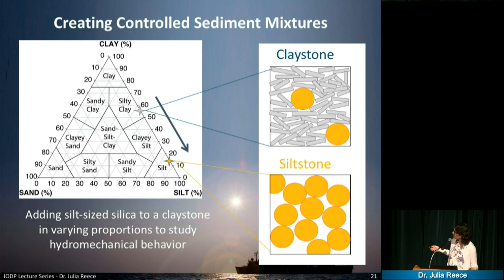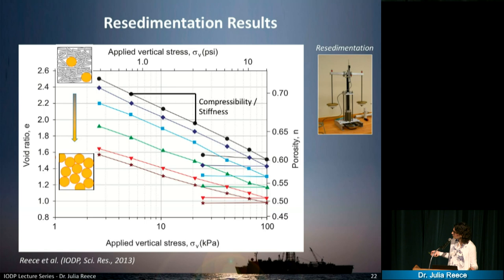And then what I did is I bought some silt off of the shelf, and I mixed it in with this mud from Japan. And so this is the silt, which lies right here. And so I mixed these two in six different fractions. And so I controlled, or I kept constant my two components. I just changed how much of each I had. And so then the result of these resedimentation tests is what you see on this graph. So we have six lines here.